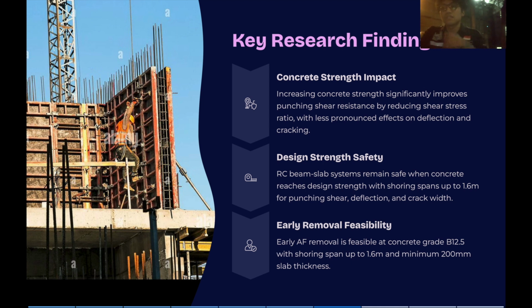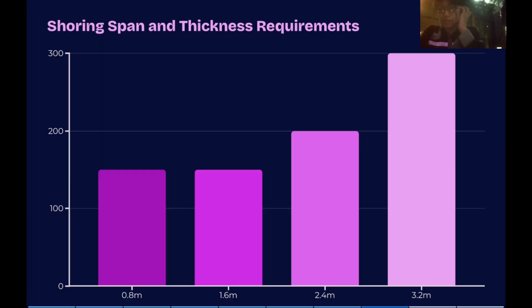Key research findings. This research yielded several key findings. Most notably, we found that increasing concrete strength significantly improves punching shear resistance. Design strength safety: the RC beam slab system remains safe when concrete reaches design strength, with shoring spans up to 1.6 meter for punching shear, deflection, and crack width. If you look at this chart, it illustrates the relationship between shoring spans and slab thickness. We discovered that early removal is feasible even when concrete reaches a grade of only B12.5, provided that the shoring span is kept up to 1.6 meter and the slab thickness is at least 200 millimeter. This gives contractors a clear safety envelope to work within.